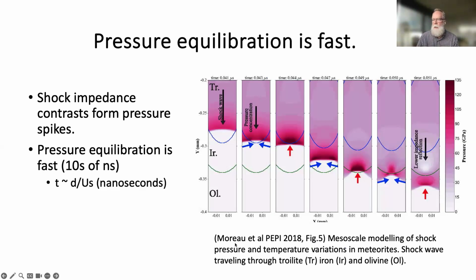Well, this is a figure from a paper by Julia Moreau. And what she did was she did mesoscale modeling of shock effects in materials to try to explain local variations in shock pressure and temperature. And I'm just going to show this because it's really interesting. This is a simple model. It's troilite on the top, and then I've got this curved interface, and then I have iron, and then olivine. And here comes the shock wave. And you can see here's the shock front, and this is showing us pressure.